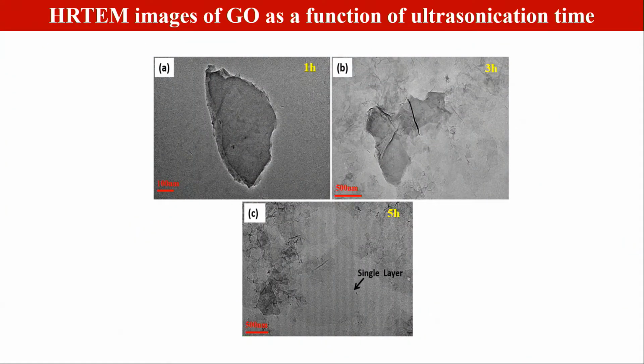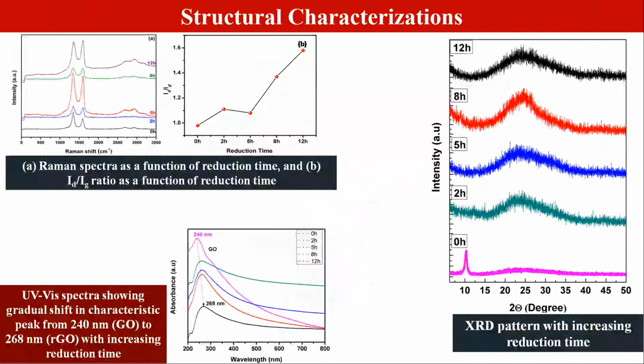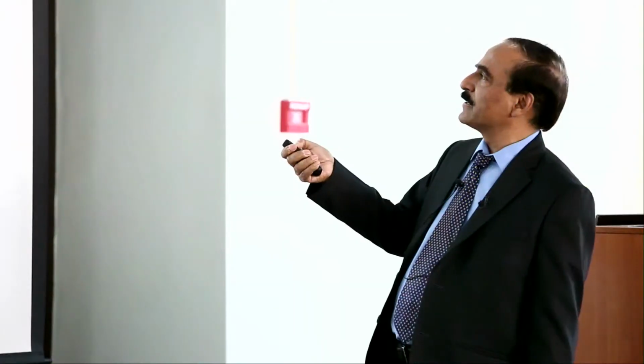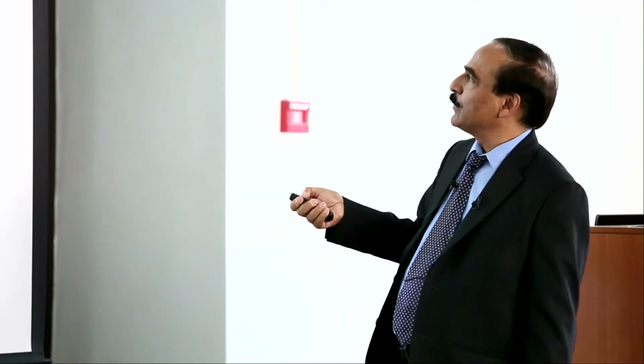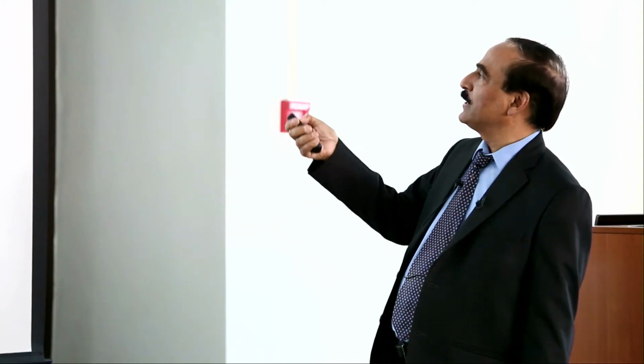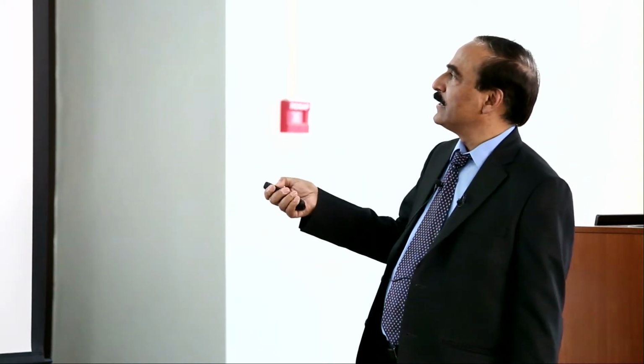This is the complementary study that we have done, on how we are creating sp2 bonding. This is the graphene structure; up to 5 hours is good. After that, if we do a longer synthesis time, then we create more damage than good. So, this is the XRD. You can see that for graphene oxide, with the functional elements on the surface, we have a peak at 12 degrees, and then if we do the chemical reduction process, with the function of power, we see this peak is getting totally reduced. This is the reduced graphene oxide pictures. This is very clear here.